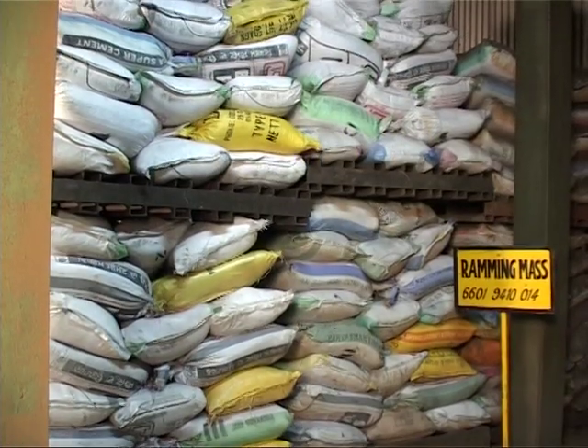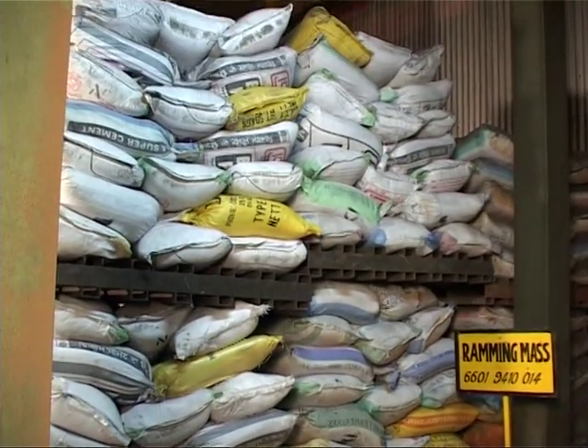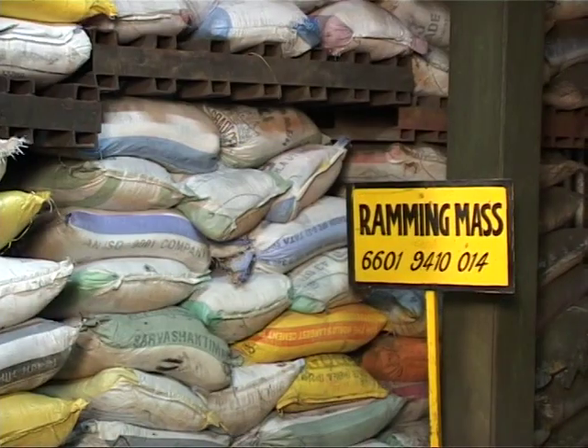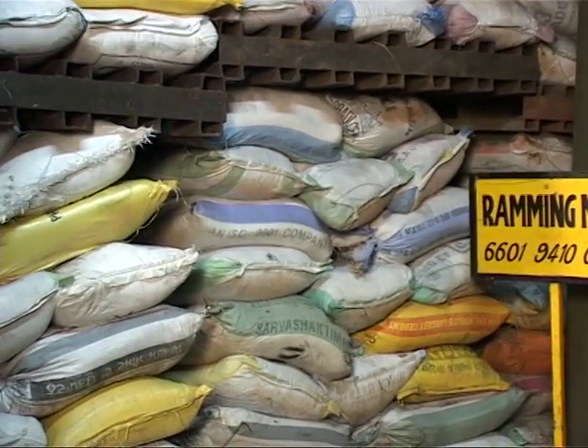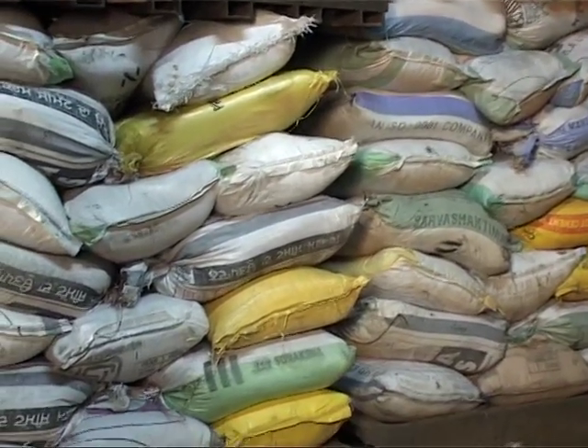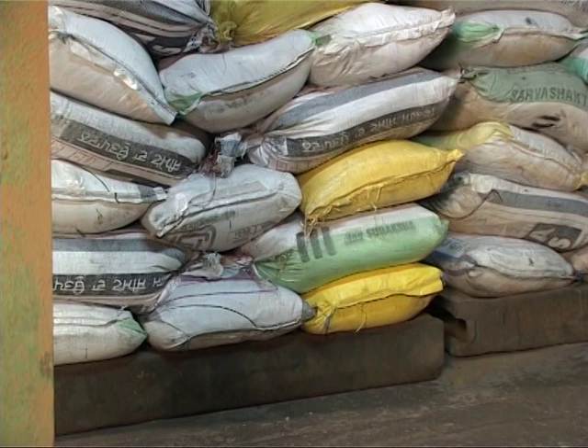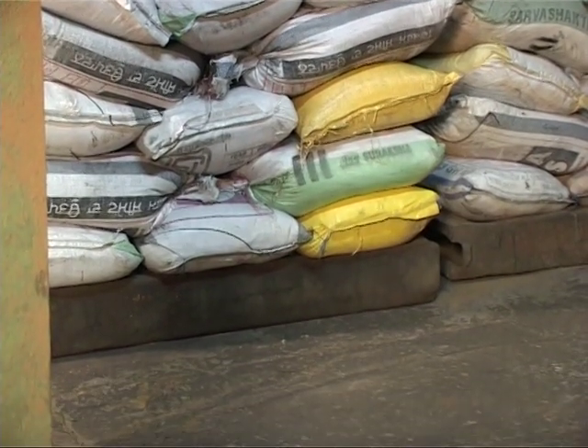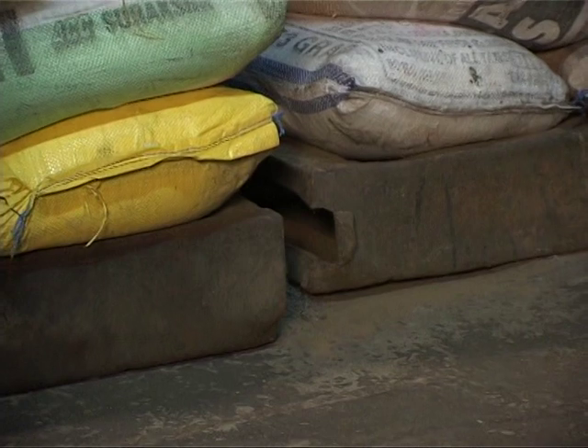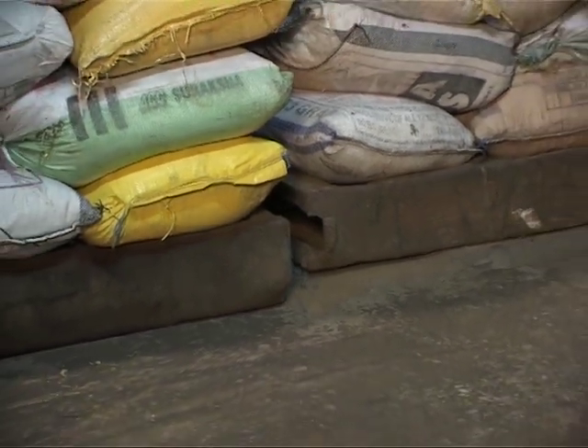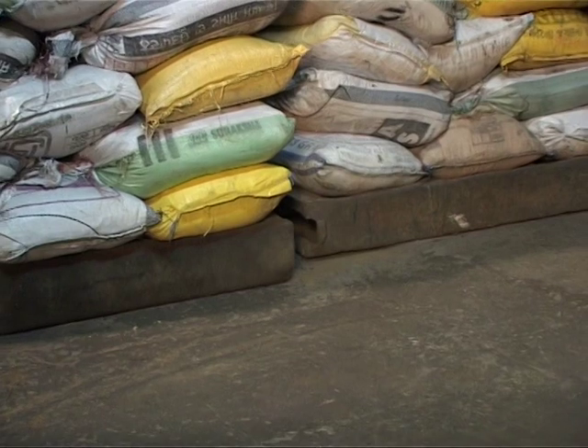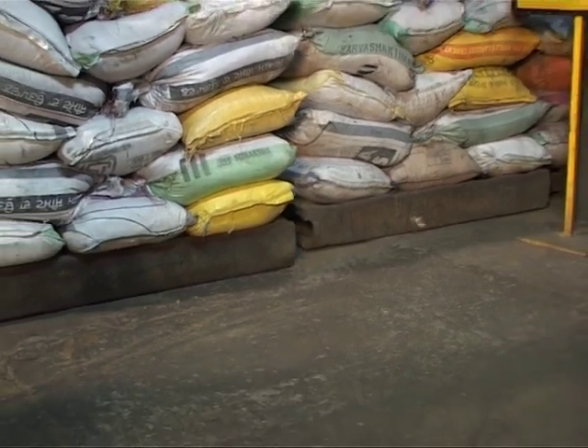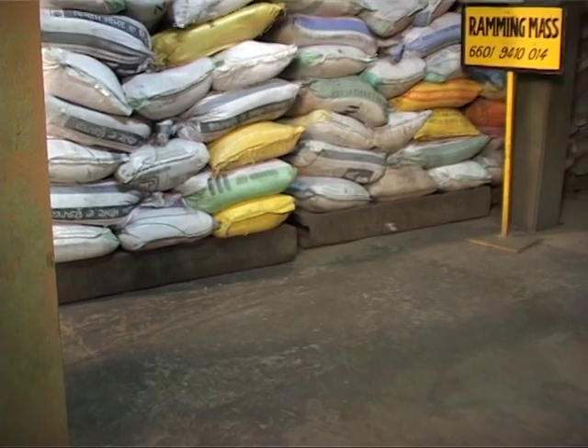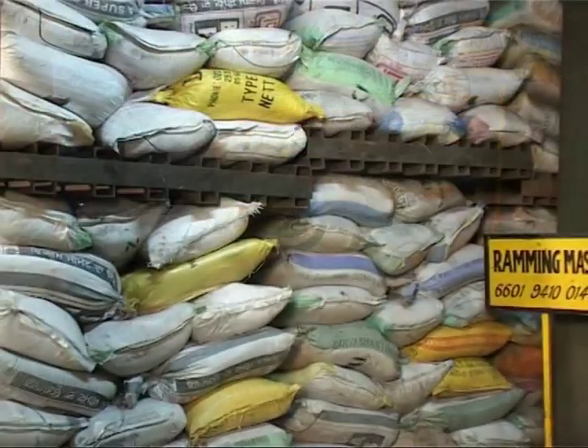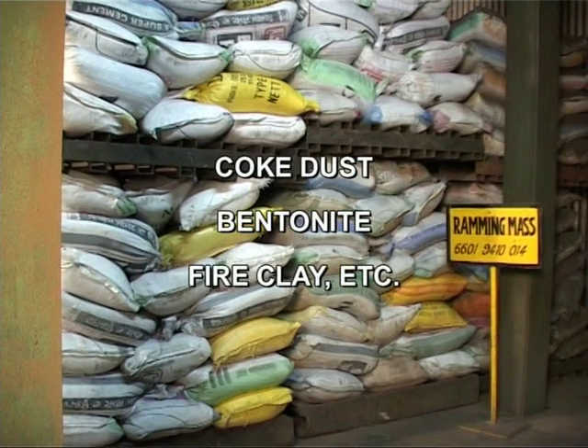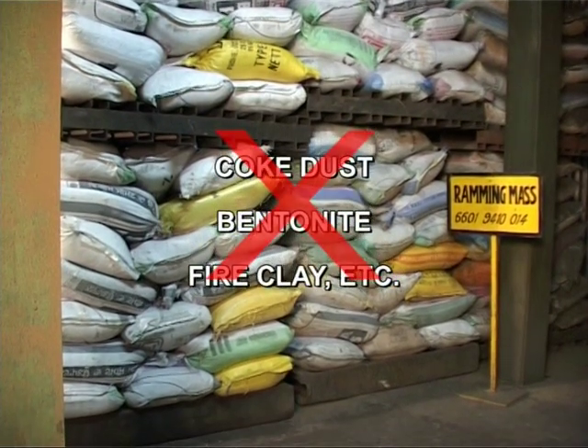Ensure sufficient stocks of proven quality and pre-tested lining material, and use on first in and first out basis. Store the material properly and have a separate store which is clean and dry for storing the ramming mass. Place logs on the floor before stacking the bags to prevent moisture absorption through the floor. Cover with tarpaulin to keep out harmful dust, and do not store coke dust, bentonite, fire clay, etc. near the ramming mass.